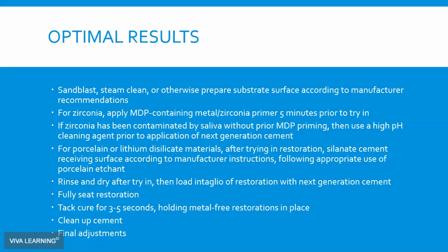Now, other people like to try it in first without priming, and that's perfectly acceptable. You can do so. But if you do that, now saliva has contaminated the zirconia, so you'll get a significant reduction in bond strength to the zirconia. So you have several options for refreshing that. You can either sandblast and wash and clean and go through all that process again. If you're really in a hurry, you can just, again, kiss the surface of the crown with your high speed with a diamond in it.